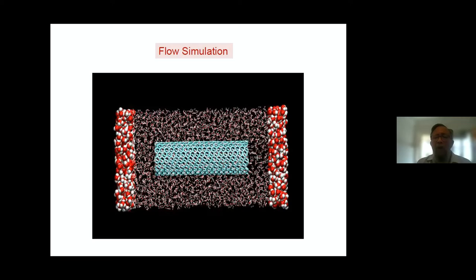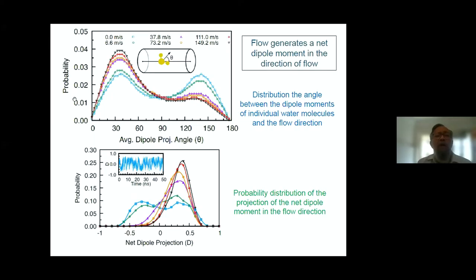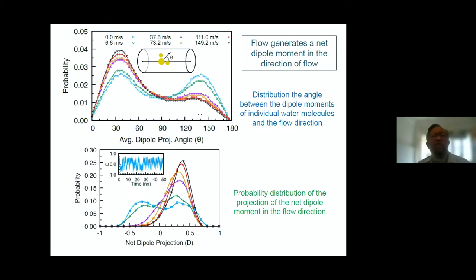There is actually alignment of the water molecules in the nanotube when the water is flowing. One result I want to show here is the probability distribution of the angle that the dipole moment of a particular water molecule makes with the axis of the nanotube. There are various curves corresponding to different flow velocities. The blue one corresponds to no flow — a stationary situation — and there you see that this distribution has two peaks: one around 40 degrees and the other around 130 degrees. This represents a bistable situation where the water molecules inside the nanotube prefer two different orientations.